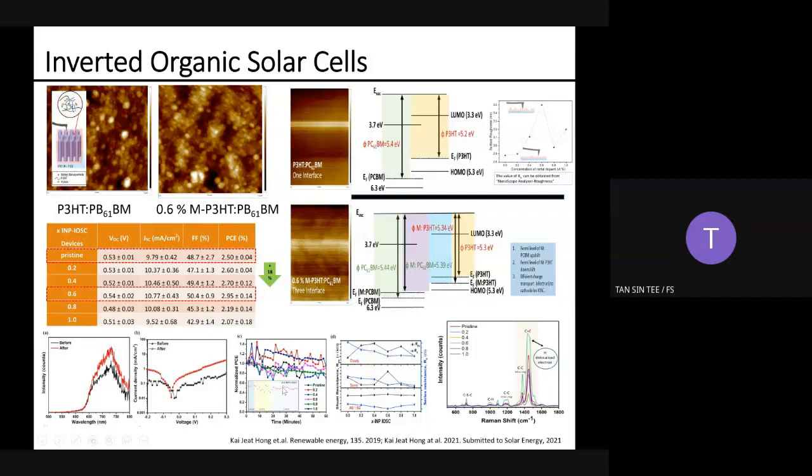Same thing, we are also using Raman analysis to prove how our indium is able to improve the crystallinity and also the charge density of the electrons from the C=C asymmetric bond here. It is found that the sample with 0.6 dopant shows a higher intensity, which proves that a higher pi delocalized electron is present in the C=C bond as compared to the pristine sample, which gives a very low intensity.